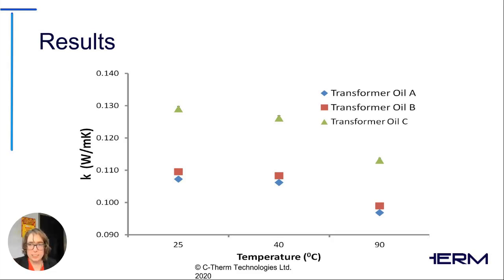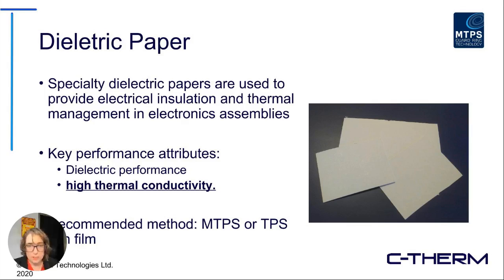And you can see that in addition to being less corrosive than the naphthenic transformer oils, the paraffinic transformer oil also has higher thermal conductivity, so it's also going to be more effective at providing that heat dissipation functionality that we look for in a transformer oil.